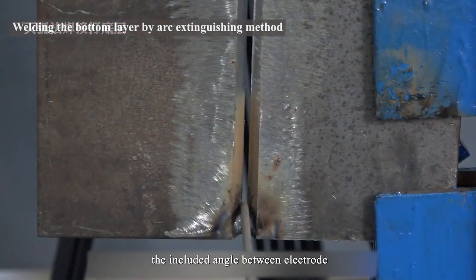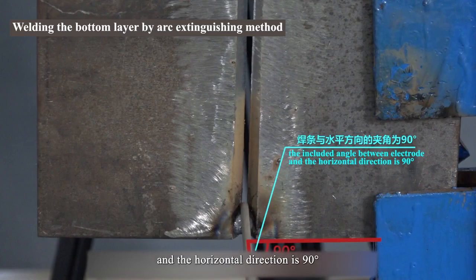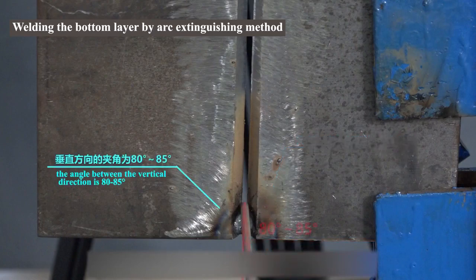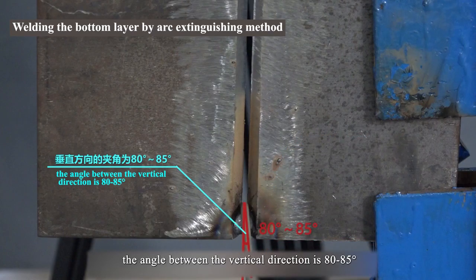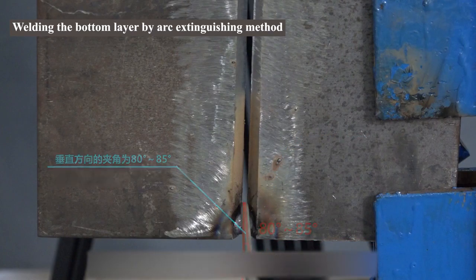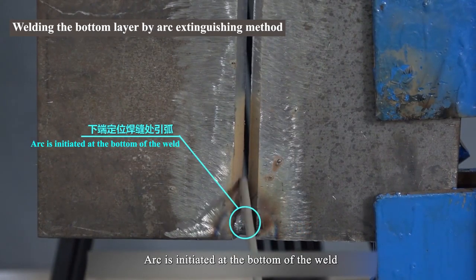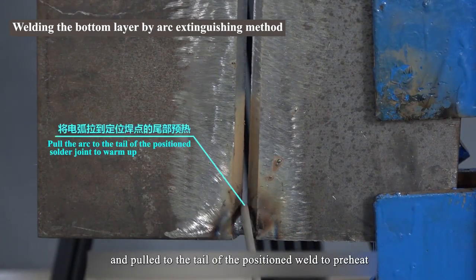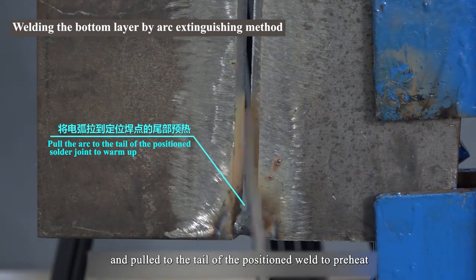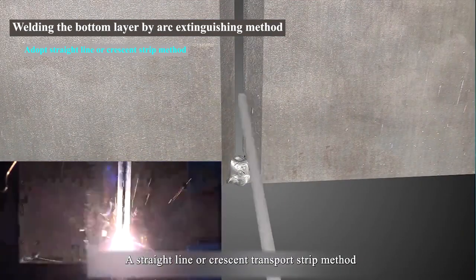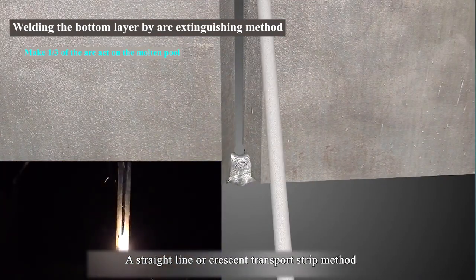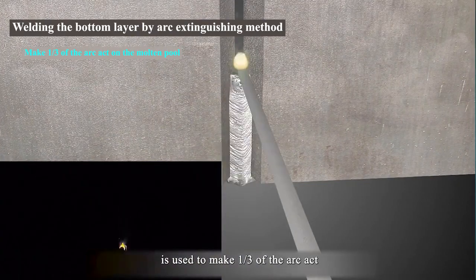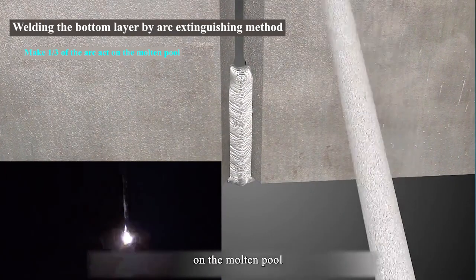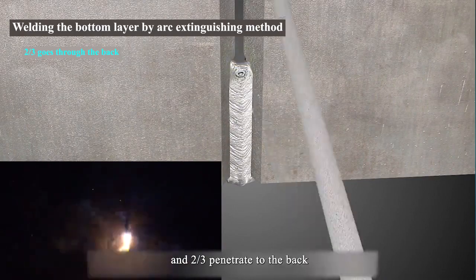When welding, the included angle between electrode and the horizontal direction is 90 degrees. Meanwhile, the angle between the vertical direction is 80 to 85 degrees. Arc is initiated at the bottom of the weld and pulled to tail of the positioned weld to preheat. A straight line or crescent transport stripe method is used to make 1/3 of the arc act on the molten pool and 2/3 penetrate to the back.